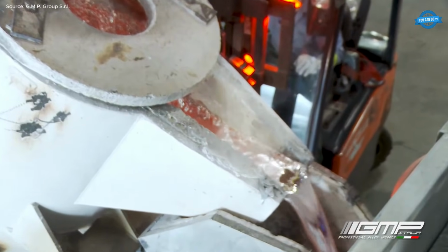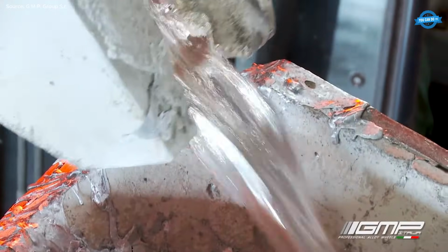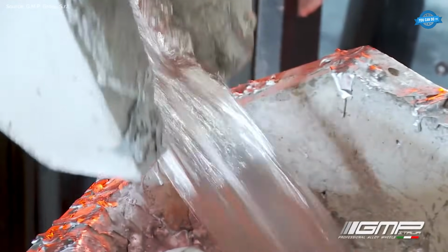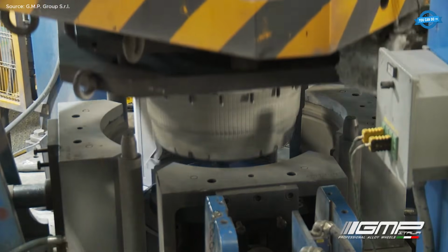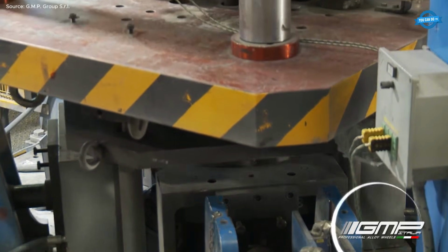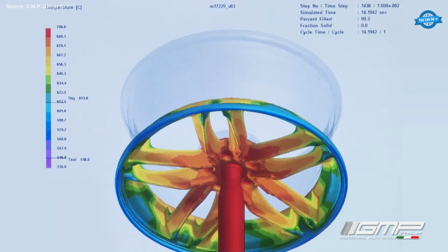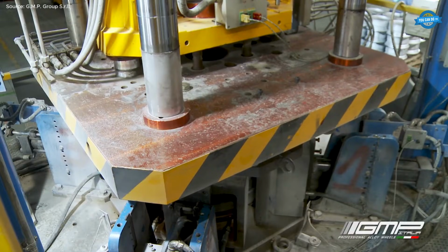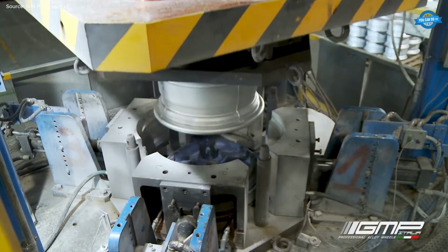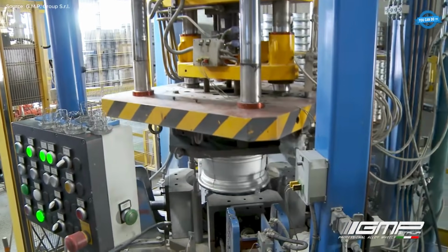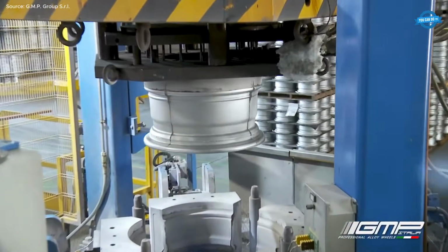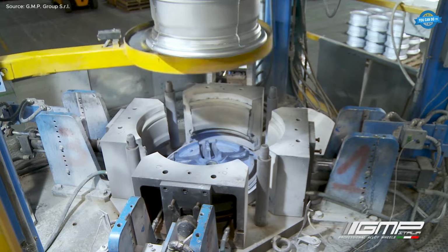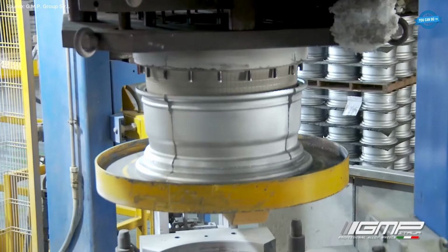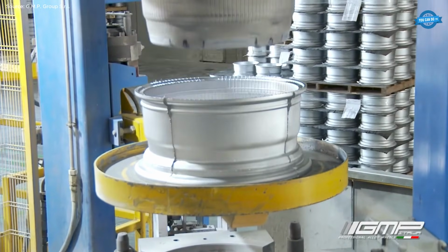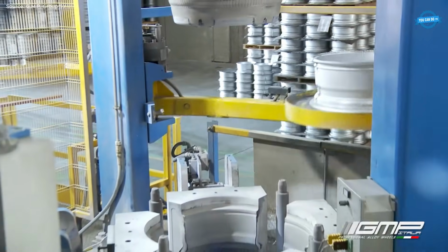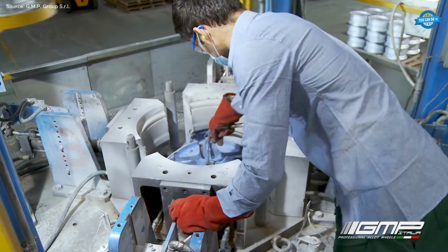At GMP Italia's Fusion Laboratory, alloy wheel manufacturing begins with controlled low-pressure casting, a process engineered for structural integrity and material purity. Aluminum alloy ingots are melted in precision-regulated furnaces, where temperature stability ensures consistent metallurgical properties. The molten alloy is then transferred into sealed low-pressure die casting systems. By forcing the metal upward into the mold under calibrated pressure, the process eliminates turbulence, reduces porosity, and forms a dense, uniform wheel structure.